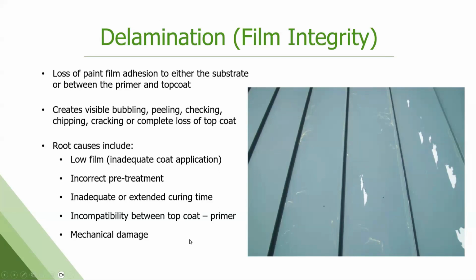Incompatibility between the top coat and primer. Maybe you used the wrong primer with your top coat that day. And then mechanical damage. This is installation damage. So this is mechanical damage in the picture. I don't know if you can see that everywhere where this paint is peeling, there's a very distinct vertical line that it's peeling off of. These were scratches that were caused during installation. You now have an opening in that coating where water and moisture and other stuff can get in there, UV, and that paint starts to peel away from that scratch. It'd be like if you went out and scratched your car. It's not going to hold up at that scratch long term like it does everywhere else.